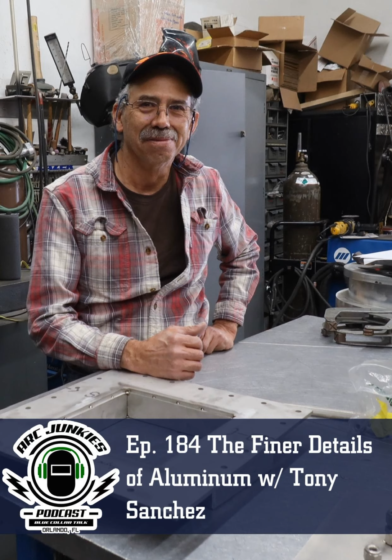And I really learned what was meant by surface tension. You know what that is, correct? Correct. Well, aluminum holds surface tension even after it's melting. And you want to talk about, I call them the jumping monkeys, where they're jumping on a bed in aluminum. It's these pockets. You could see them come up and push a little on the surface. And you're almost waiting for it to pop, but it doesn't, and it goes away. So you roll your arc over a little bit and kind of force that heat into it. And you watch it do it a little bit more. And then all of a sudden it almost settles.